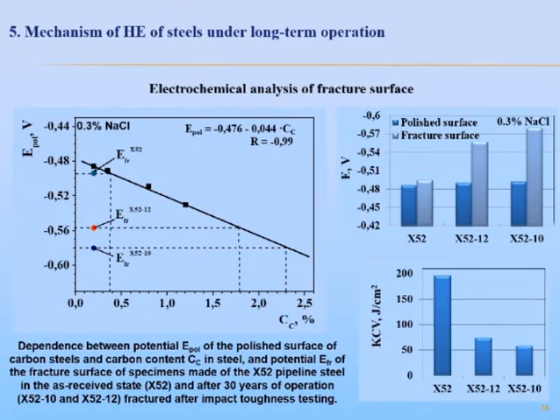And it should also be noted that under such embrittlement, a decrease in brittle fracture resistance of metal caused by long-term operation should be expected for both intergranular and transgranular fracture modes.